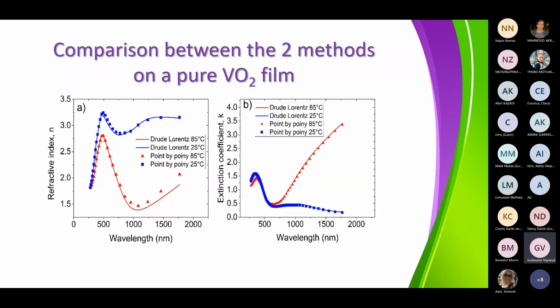Here we can also see that for the extinction coefficient K of the samples at 25 degrees, there is absorption in the UV, and the film is almost transparent in the infrared range. But if the temperature is increased to 85 degrees, there is a strong increase of the absorption defined by K, which means that the sample becomes a conductor, and most of the incident beam is reflected.